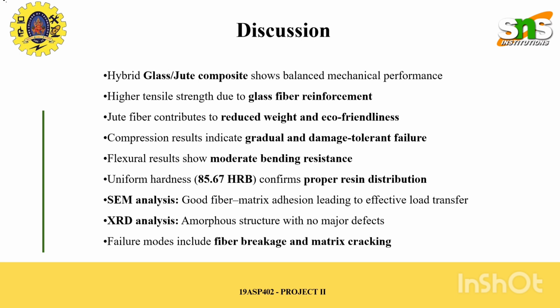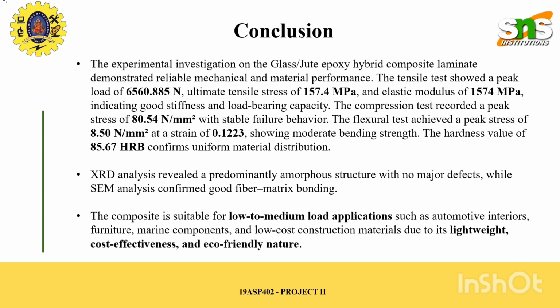The hardness results confirm proper resin distribution, while SEM analysis shows strong fiber matrix bonding. XRD results indicate a defect-free structure. The failure modes observed include fiber breakage and matrix cracking, which are typical and acceptable for composite materials under load.